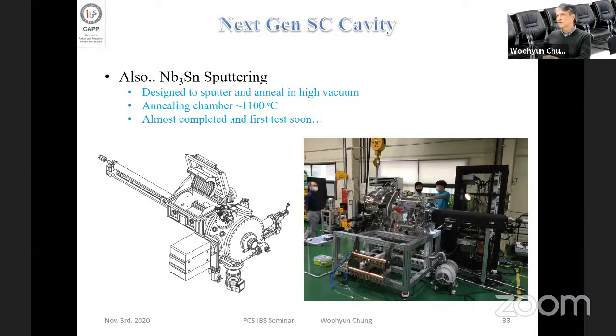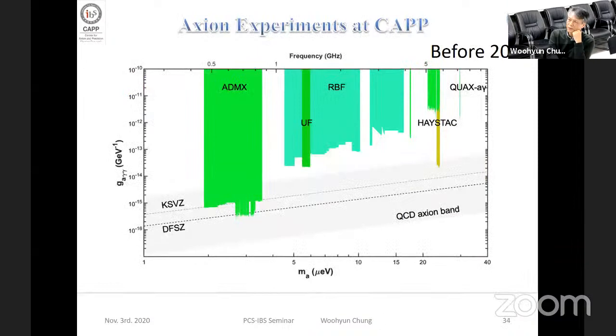And also, we are doing niobium tin sputtering too, because we think niobium tin is still a very good material for many areas. So we fabricated the niobium tin sputtering machine. It's kind of hard to sputter it and then transfer to the annealing chamber, and the annealing chamber also has to be at very high temperature. So it took us more than 6 months to complete it, and it's almost done. We're going to do the first test probably next week. All in all, our superconducting cavity R&D is going very well and is promising.